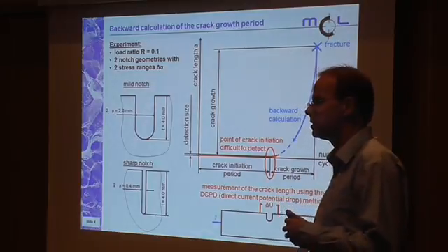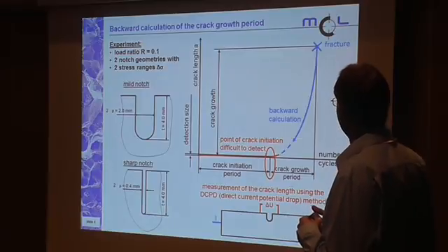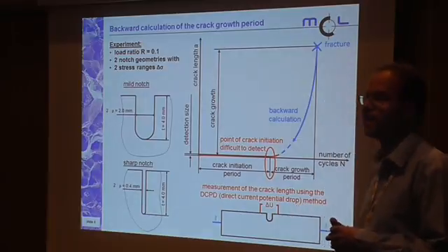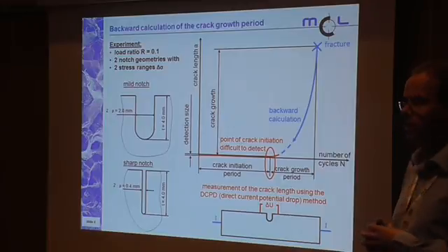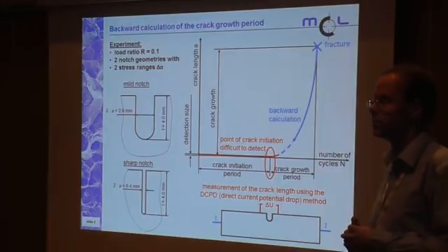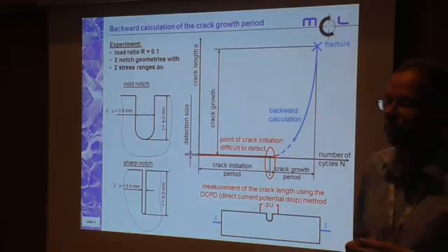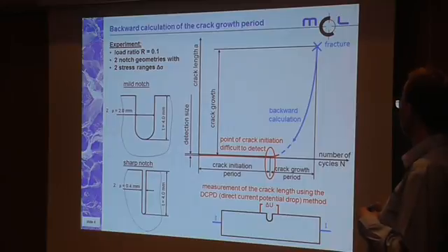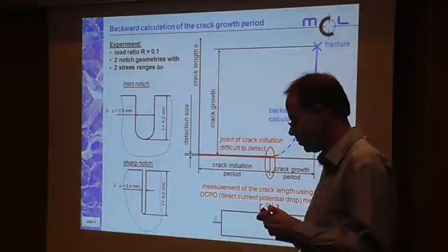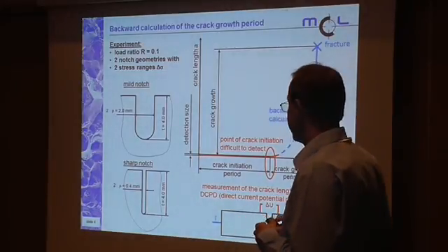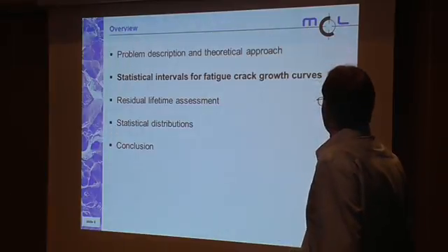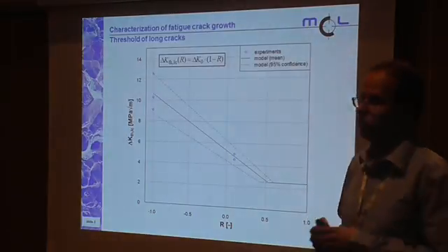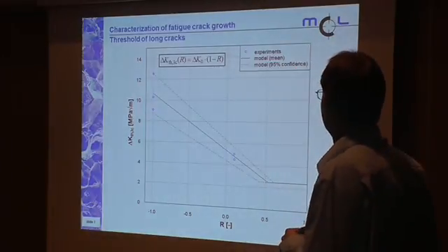Here comes the idea of this talk today, that is, we can of course calculate rather precisely the crack growth regime, especially if we start at the end point where we know the size of the crack upon fracture. And so we can do the back calculation up to a certain point of crack initiation if we know the crack growth behavior exactly. So that's why we were trying to get statistical intervals for those crack growth curves.